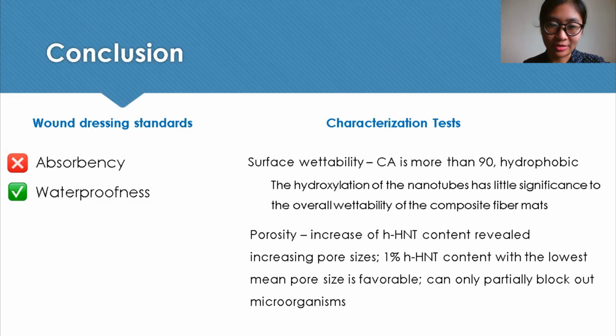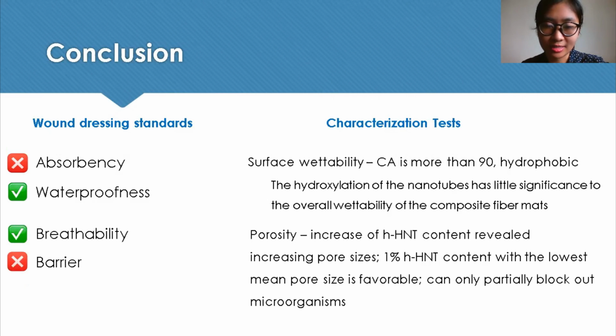Due to the porous nature of the e-spun material, it can allow air to pass through to give breathability to the wound surface. But it is still limited as it cannot absorb excess wound exudates, and it cannot totally block out all microorganisms due to its bigger pore sizes, or it can only partially block those microorganisms out. So although the fabricated PLA HHNT composite mats did not possess sufficient properties as a wound dressing, data shown here have significant importance that can aid to further tune the properties of fibrous biomaterials.